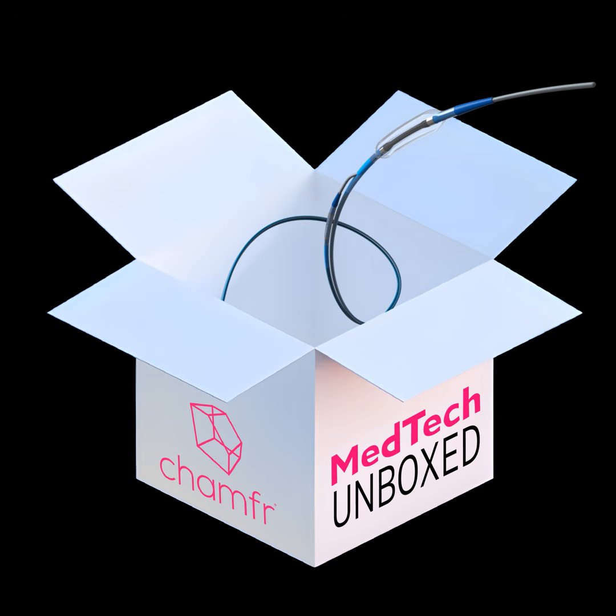So what we're trying to do, looking at the thermoplastic liner, is really to increase the robustness to avoid delamination, because I think this is the number one enemy of PTFE from the manufacturing perspective. So if this type of new material is thermoplastic, or ideally even nylon based, and compatible with the rest of the architecture, then you can eliminate delamination, especially after deflection, after multiple cycling of the catheter. So I don't think PTFE became a worse material, but engineering requirements have simply evolved to a different architecture that makes us look at other options.